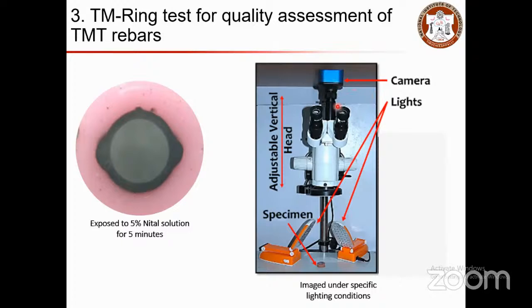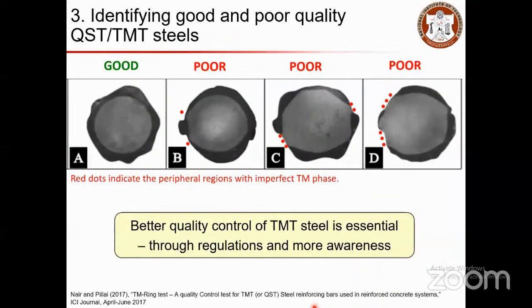You have a camera and lights placed on it, so the image under the specific lighting conditions will be helpful to look at the TM outer and FP inner phase. Here are some examples where you can see good TM bars and poor TM bars. Nowadays you might have seen a lot of advertisements saying that the TMT bars are qualifying the TM ring test. Those are based on this test method. You cut it, then you see the microstructure to indicate the TM ring outer surface and FP inner surface. This shows a good uniform hardened outer surface of the TM phase and then the inner core FP phase.